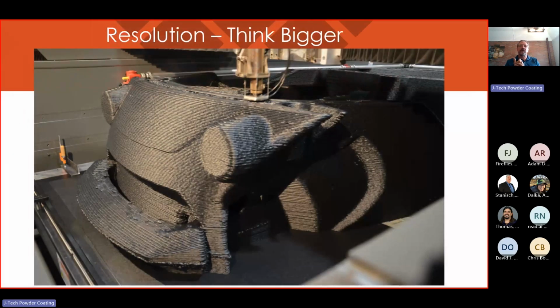Printers with very high extrusion rates also have much larger nozzle sizes and print much thicker layers. This is the Strati, the first 3D printed car, being printed on a CI BAAM, half-inch nozzle and about a 3/16 inch layer. The resolution is not the most attractive.